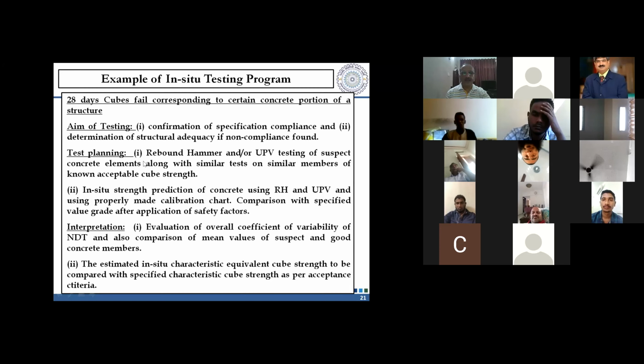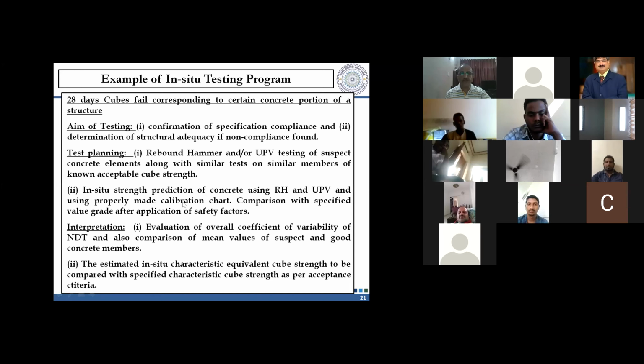And then testing of suspect concrete elements. You will perform this test on the suspect concrete. You will also perform this test on the concrete whose cubes were found to be all right, meaning good concrete. So you will perform this test on both the concretes. In situ strength prediction of concrete: this is about the variability first. Second, you will go ahead and also find out, based on this rebound hammer and UPV, using site-made charts. After applying correction factors, you will actually find out the grade fck value also.